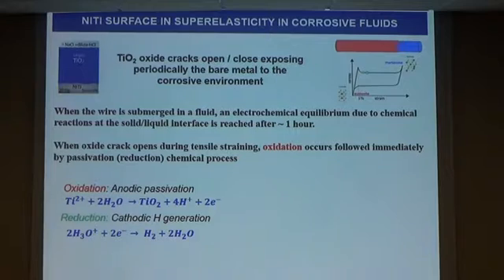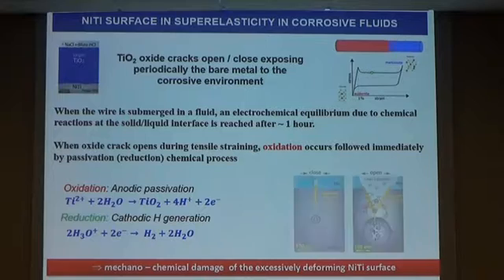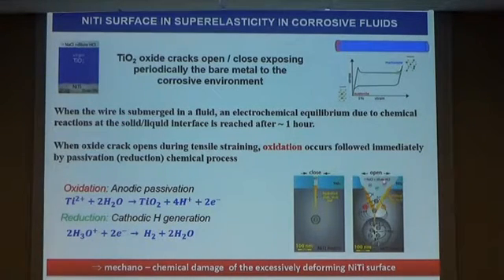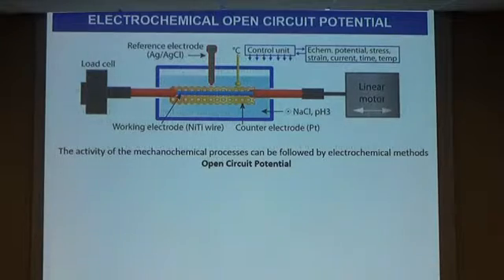So let's think a little bit more about this mode of periodically opening and closing cracks, because now you are with the electrochemistry, and if you open the crack, you let the fluid be in contact with the bare metal, and immediately these chemical reactions will start. And so here, this is like this figure, and we think that this was already published in the literature. Actually, this is what damages the material, but it was not clear how.